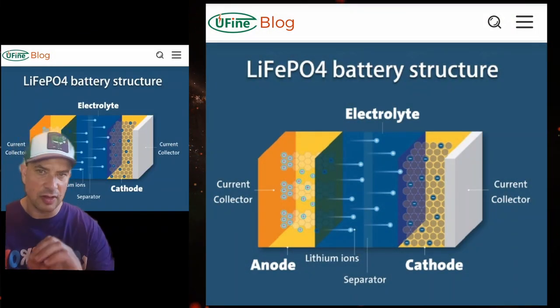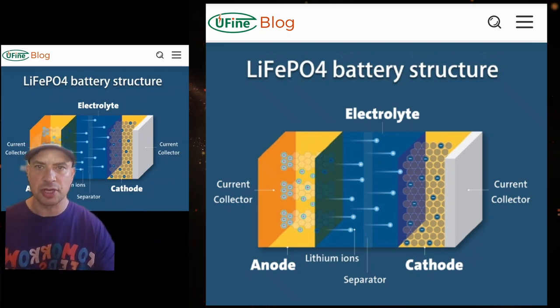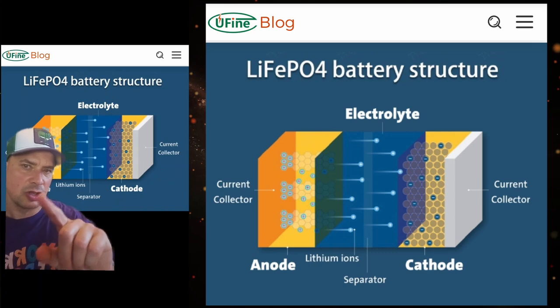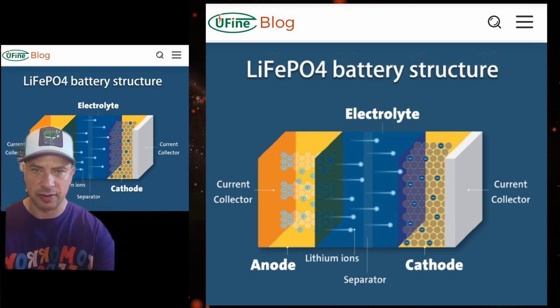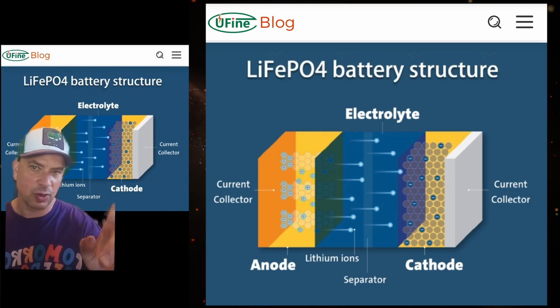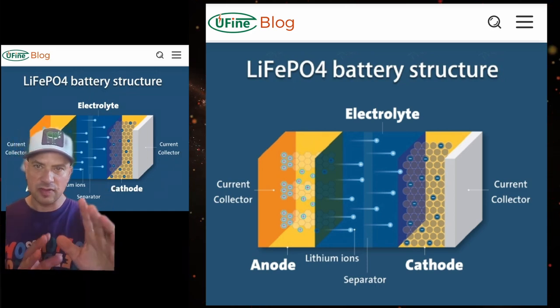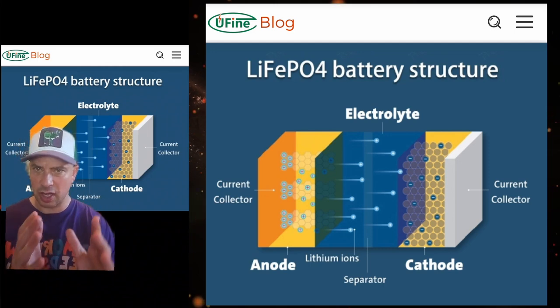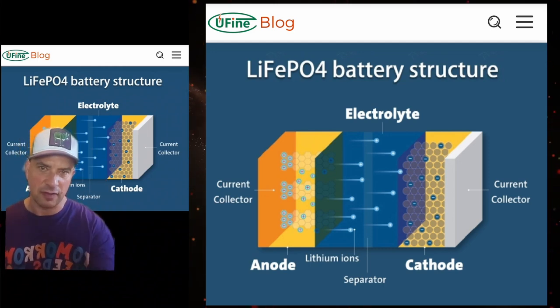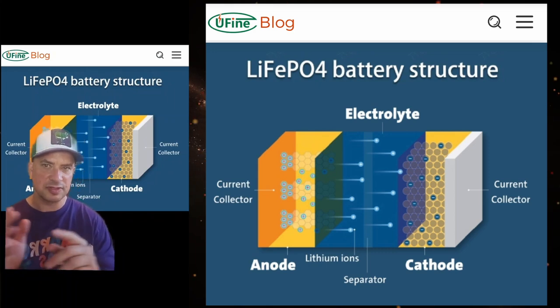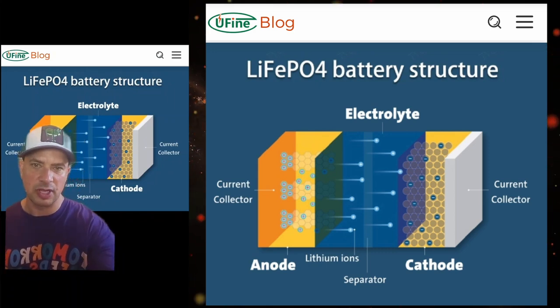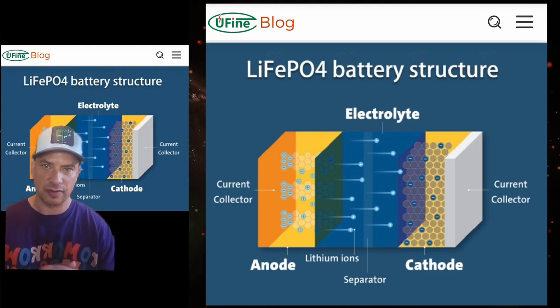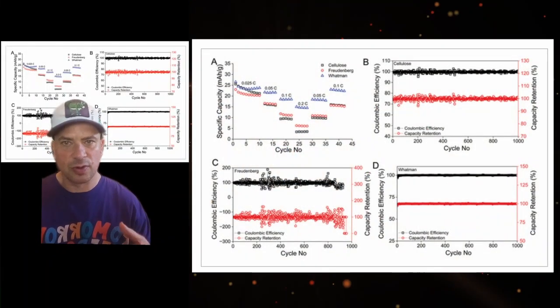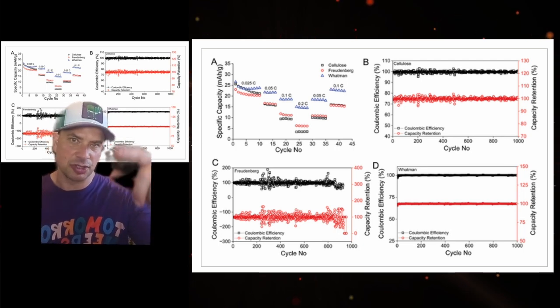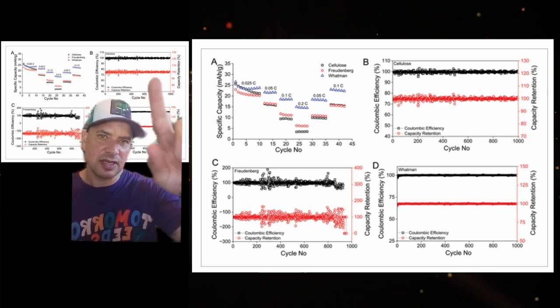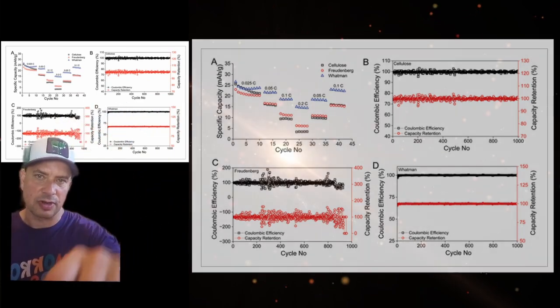Now, I mentioned earlier that when a battery runs and when it's recharged, the volume changes. And it's basically because you're moving lithium ions from one side to the other. So when it discharges, they go one way, and when it recharges, they go the other way. And in the process of that happening, you can cause those other things that are built into those electrodes to fall off. So how well it maintains through these cycles of use and recharge is very important for any battery. In fact, that's what determines the life of the battery. So they ran these through 1,000 cycles of charge and use, charge and use. And as you can see, they didn't lose any capacity to produce power.